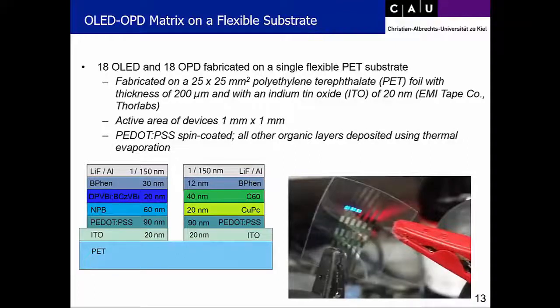This is the OPD stack, again based on the copper phthalocyanine C60 material as active material. So these two stacks, we now fabricated on PET foil. The PET foil had a thickness of 200 microns, and it has an indium tin oxide layer of 20 nanometers on top. The active area of each of these devices is 1 millimeter by 1 millimeter. So with this masking here, we realized 18 OLEDs and 18 OPDs on a single substrate now. And so with this, we characterized now these devices.